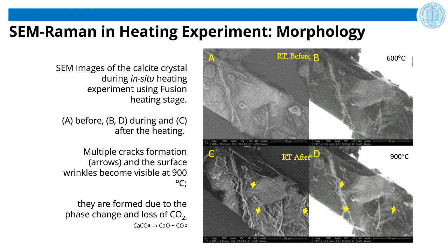The slide shows in situ SEM secondary electron images of the calcite crystal before (A), during (B, D), and after (C) the heating experiment. Multiple cracks, shown with arrows, and surface wrinkles due to the loss of carbon dioxide become visible at 900 centigrade. The next slide shows Raman results on a calcite sample under heating.